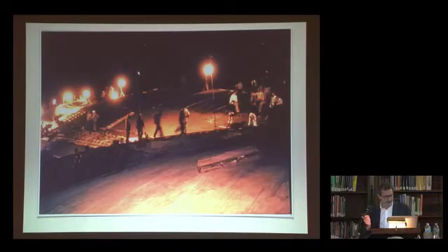And because of some concrete damage, I think, that happened at the United Terminal, that was happening simultaneously, the Port Authority got very nervous about this building all of a sudden. And they got so concerned that they hired a specialist from NYU who attached strain gauges to different sections of the rebar and were taking measurements to make sure that the loads were one way when the rebar was not loaded. They were measured when the rebar was loaded, and then they were measuring very carefully as the scaffolding was being removed. They also had points on the building that they were shooting constantly to make sure that nothing was moving.